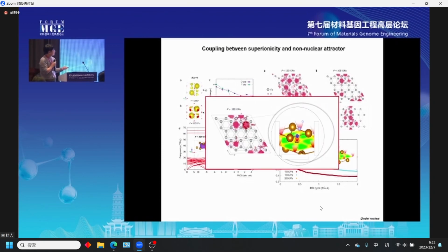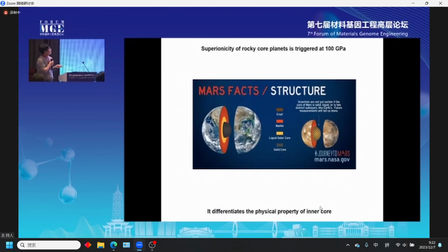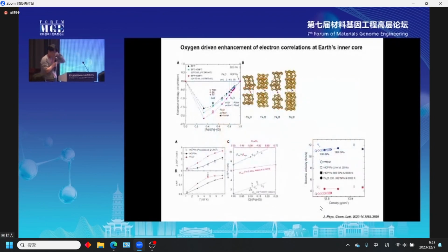And this may be important for understanding the difference between Mars and Earth, because Earth's inner core has around 300 gigapascal pressure, but Mars's inner core has much less, below 100 gigapascal. So iron hydride in Earth's core should have this superionic effect, while Mars doesn't have such an effect. So we try to understand what physical phenomena differ between the Mars and Earth inner cores, so we can differentiate the inner state of rocky planets.